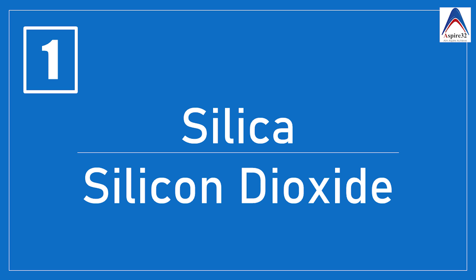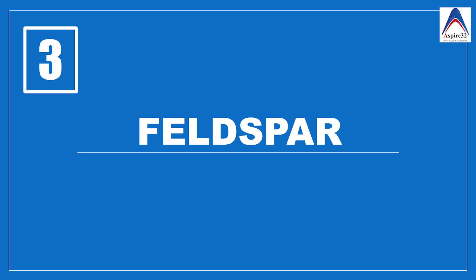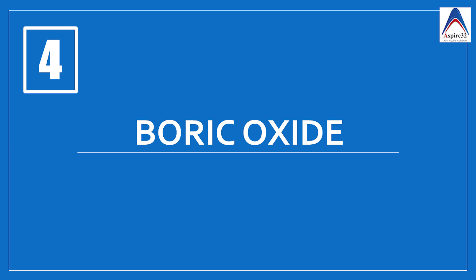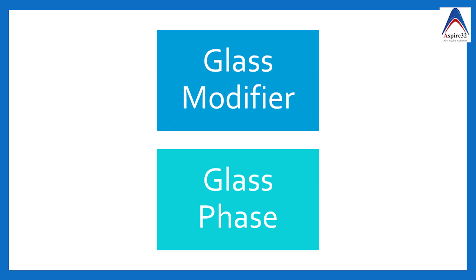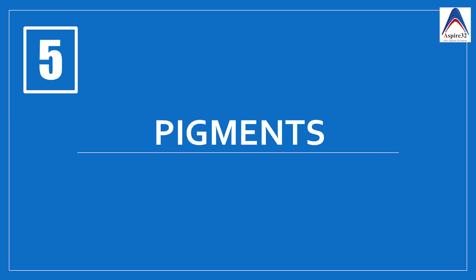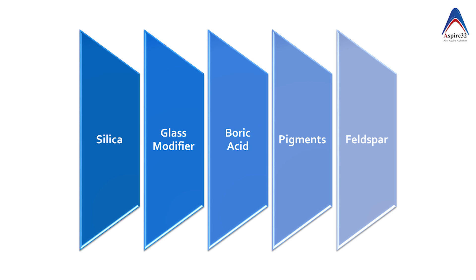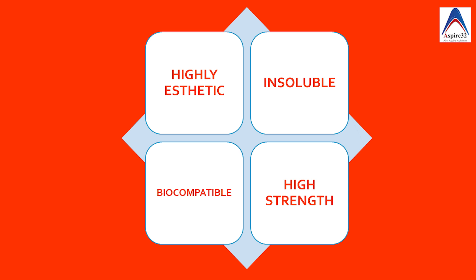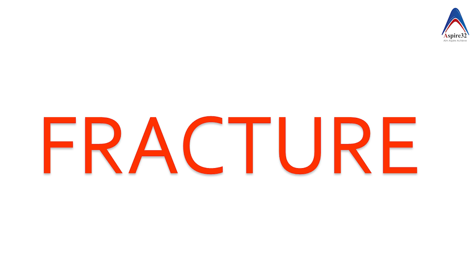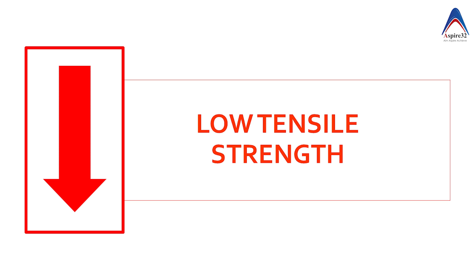To revise quickly: we started with non-crystalline silica, added glass modifiers to reduce fusion temperature, and then added feldspar. Along with these three major components, boric oxide was also added — it acts as a glass modifier and forms a glass phase that facilitates movement of silica particles. Pigments were also added for different shades. The world finally had feldspathic ceramic. However, crowns made purely of feldspathic ceramic used to fracture very commonly because its compressive strength was good but tensile strength was very low, making it very brittle.